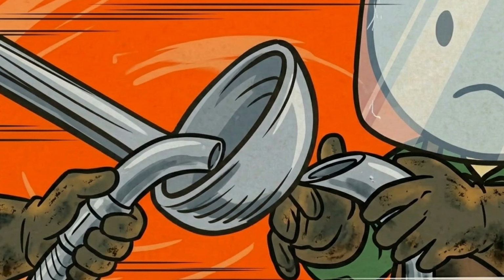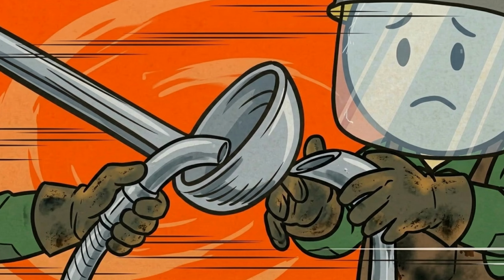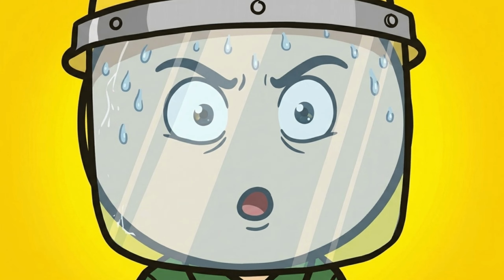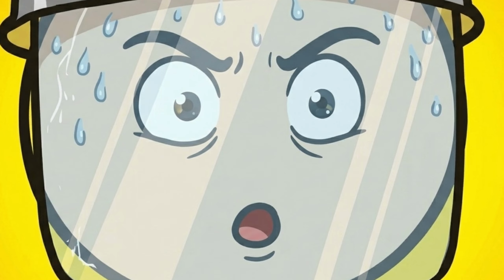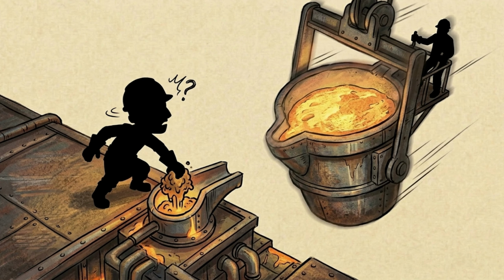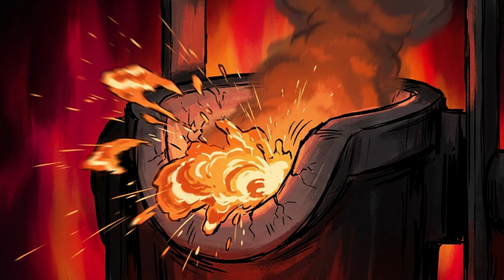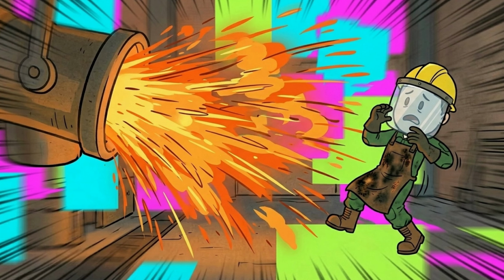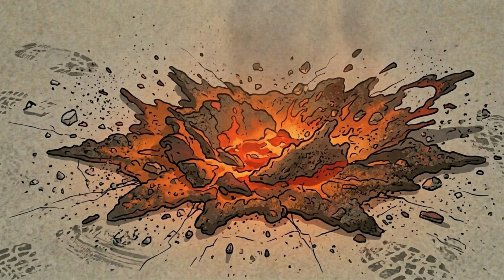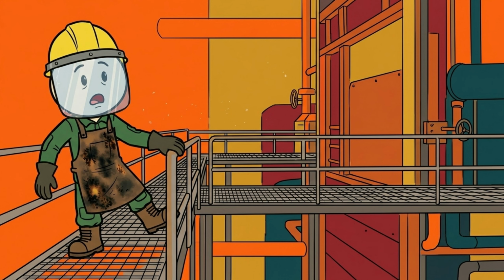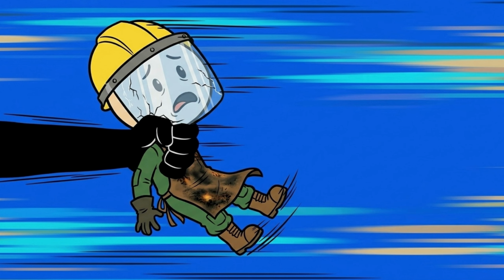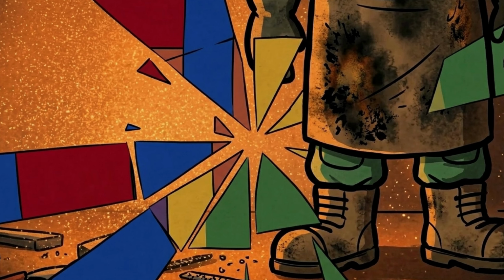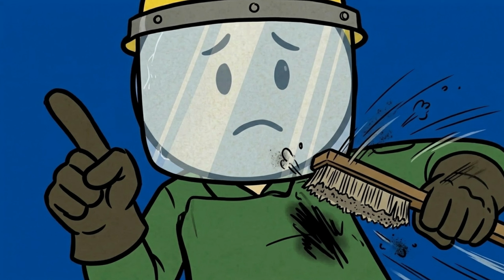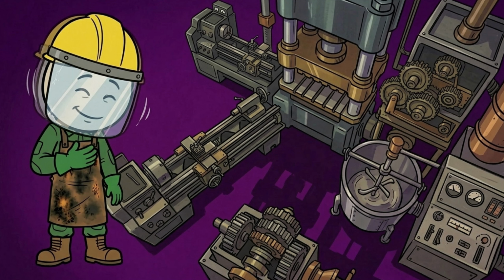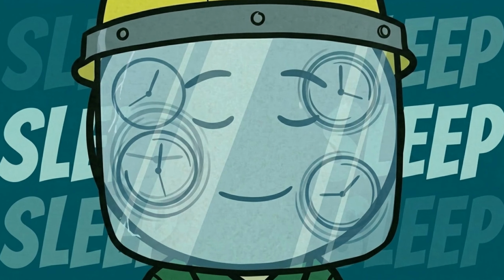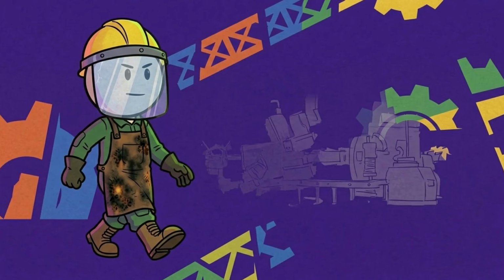And then comes the shift that tells you whether you have a career. You're raking slag off the tap, and a runner clogs, and someone behind you swings the ladle before you've cleared the spout. The metal kicks. A gout of slag comes off the lip and lands where your boot was a half second before. Somebody grabs your collar and hauls you back. You keep both legs, and you finish the heat with a scorch mark on your bib instead of a burn down to the bone. You stop sleeping badly on the nights, and you can't say which week it stopped.